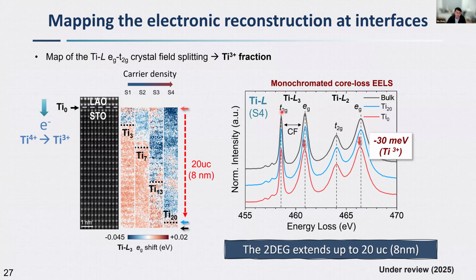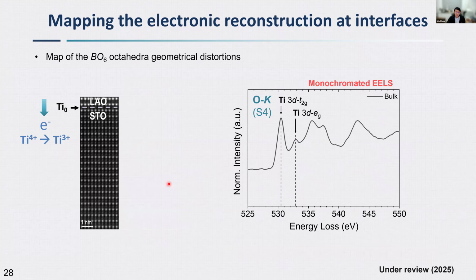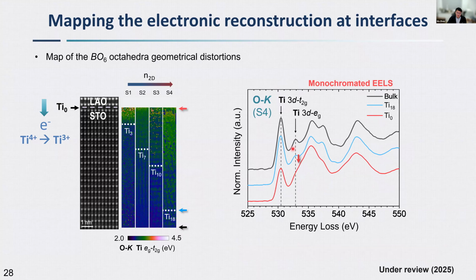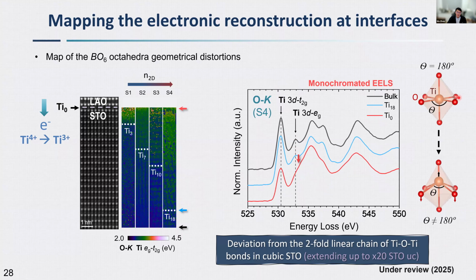So if you map out the distance between the T2G and the EG, you can see that with the increase of charge carrier density, we see a progressive increase of the 2D electron gas layer thickness. And we can also see that from the oxygen K edge, where this shoulder peak gradually increases in energy and merges all the way to the main peak. And this is an indication of the structural distortion, more specifically TiO6 octahedral distortion. So this is an indication that we have structural distortion due to the two-dimensional electron gas.